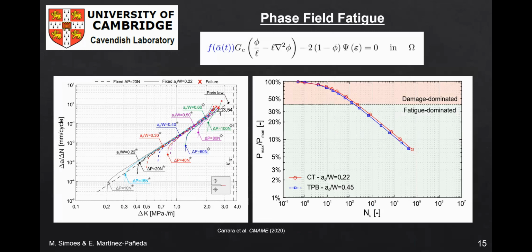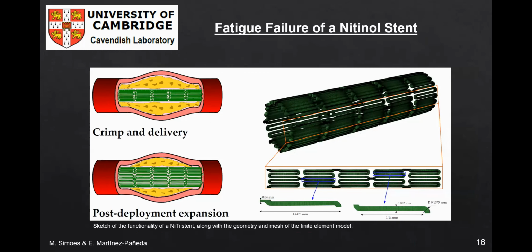So let me now show you some fatigue results. Phase field fracture models have also been extended to model fatigue crack growth. The idea is to define a fatigue degradation function that reduces the toughness of the material with increasing number of cycles. And the beauty of it is that well-known fatigue behavior, such as Paris' law or SN curves, can be predicted by our model. So they are an output of the model, not an input, as is typically the case.